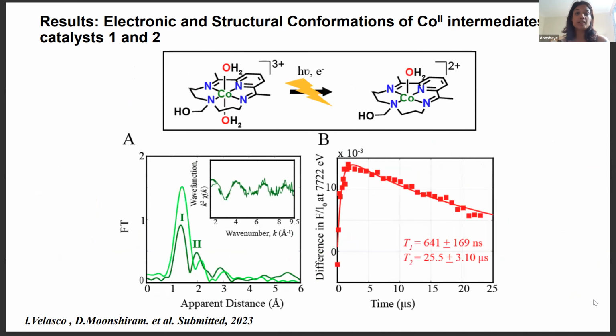And even though the excited state fraction was very low, by comparing the spectra of the photoreduced cobalt-2 to a reference cobalt-2 complex that was chemically generated, we found that the excited state fraction was around 4 to 5%, even though this is quite low. We were able to reconstruct the laser-on spectra of the cobalt-2 complex. And indeed, we see two peaks, 1 and 2, which correspond to the cobalt-nitrogen and the much more elongated cobalt-oxygen species of around 2.22 angstrom. And this rules out the formation of a square planar geometry and shows that we have a square pyramidal complex where the water is attached to the metal center as a loose contact.